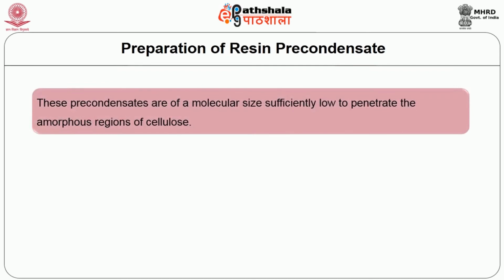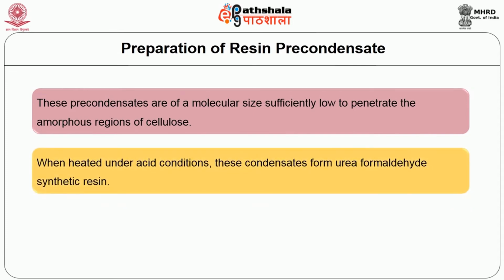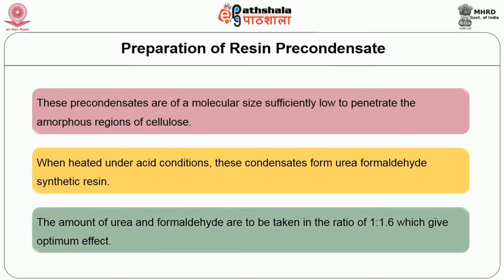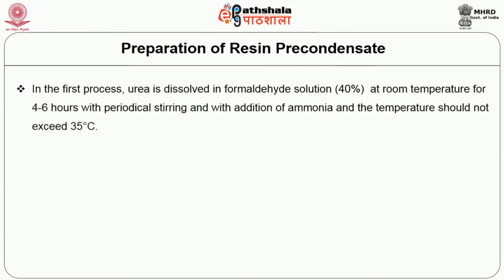These precondensates are of a molecular size sufficiently low to penetrate the amorphous regions of cellulose. When heated under acid conditions, these condensates form urea formaldehyde synthetic resin. The amount of urea and formaldehyde to be taken in the ratio 1:1.6, which gives optimum effect. In the first process, urea is dissolved in formaldehyde solution 40% at room temperature for 4 to 6 hours with periodical stirring, and with addition of ammonia, and the temperature should not exceed 35 degrees centigrade.